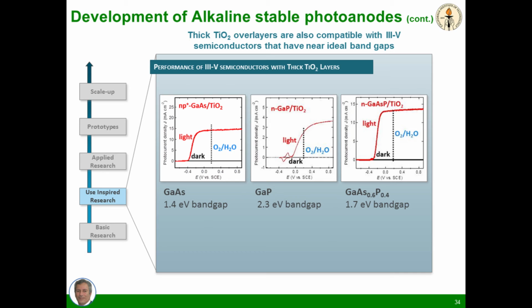We then applied this to gallium arsenide, gallium phosphide, gallium arsenide phosphide, and showed we could stabilize the entire class of small band gap semiconducting materials that had heretofore been off the table, thought to be fundamentally inaccessible since 1955 when Gerischer first found that they corroded.